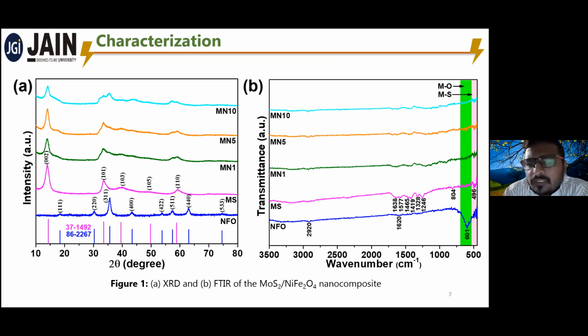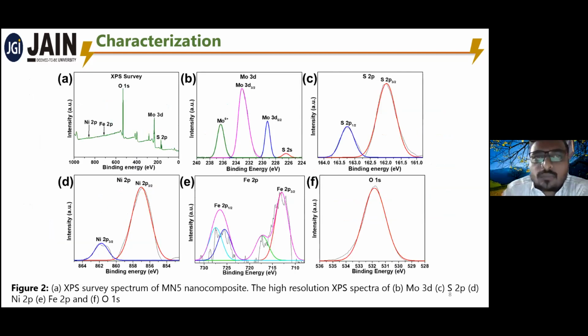Other than this, the peaks around 1200 and 1600 represent the stretching and bending vibrations of the water molecule. In the nanocomposites, all the peaks of MoS2 and NiFe2O4 are observed, with less intensity. There may be interactions, and it is evidence that interactions between MoS2 and NiFe2O4 take place. To further confirm the structure of MoS2 and NiFe2O4, we use the XPS analysis technique.